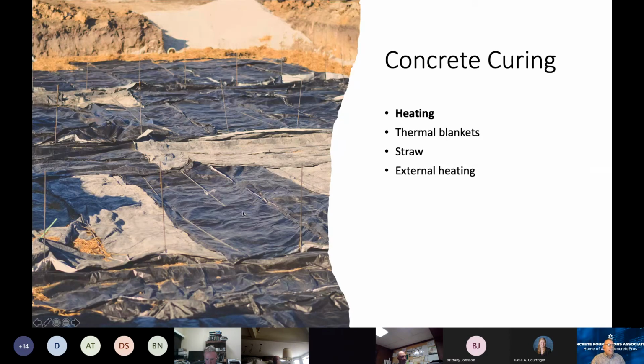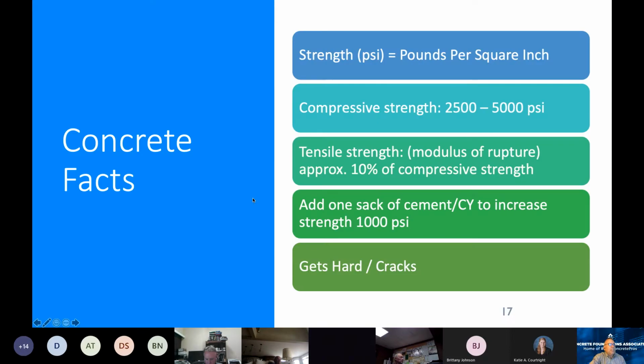So one way we protect concrete in curing and keep the temperature there, you guys are throughout a market that, like Iowa, is affected by cold weather. And so this is not an uncommon scene out on construction sites during the winter, putting thermal blankets out or straw on footings, or maybe even putting a tent up and using some external heat to keep the temperature of the concrete buoyed up so that we can control its maturity, its strength gain. We can also, on the other side of it, get into the summer months, and we're trying to slow that heat gain down, because on a 100-degree Colorado day with the sun beating down on it, as dry as your environment is, your climate is going to suck that moisture right out of the concrete, which is going to mean it's going to get to its finite strength cap, or its ultimate strength cap, more quickly, but it's also going to dimensionally change more quickly. And that's what we're setting the stage for as we begin to look in on cracking.